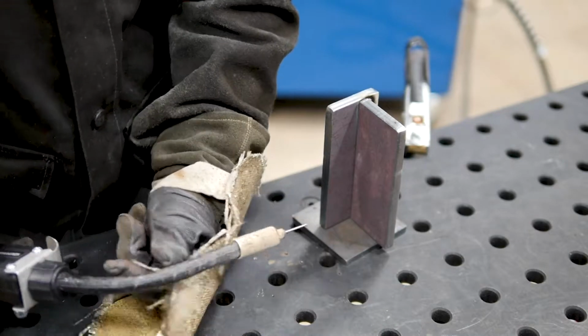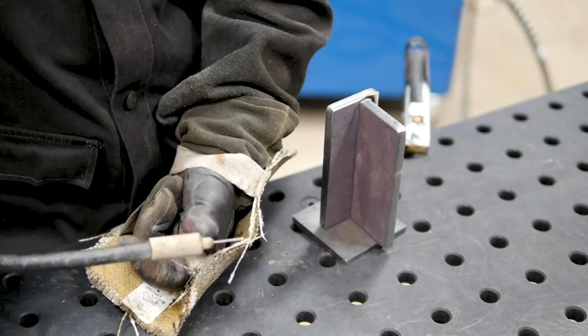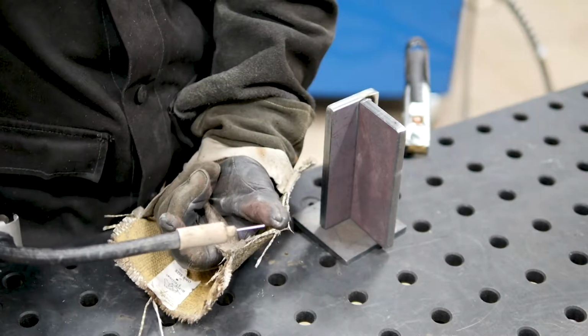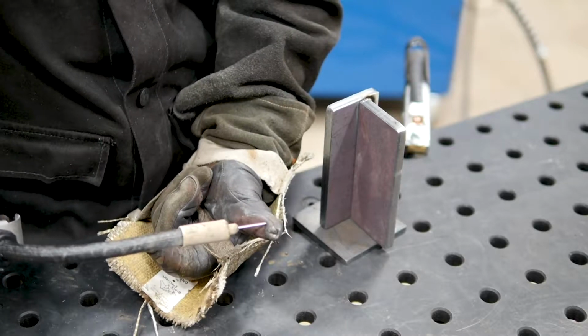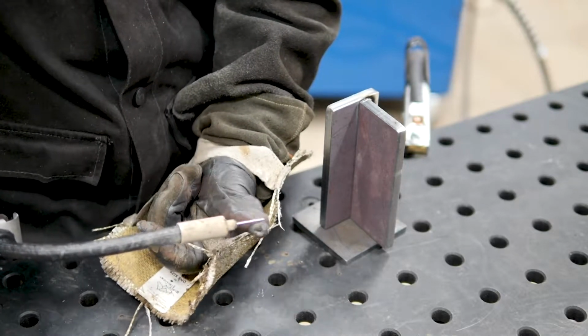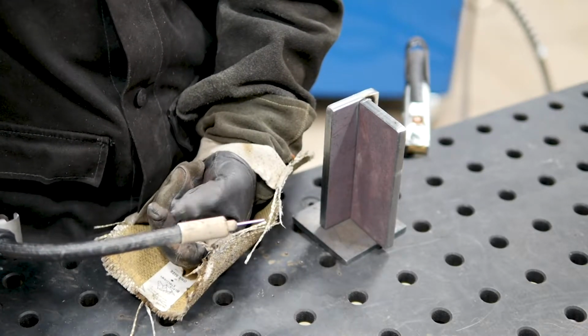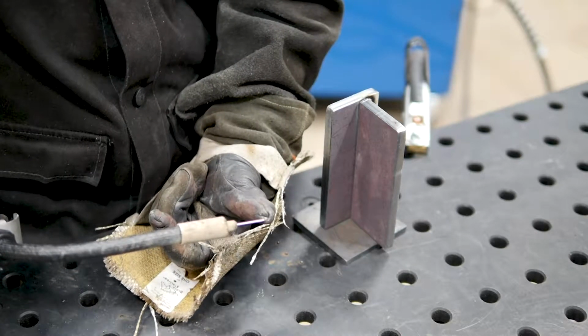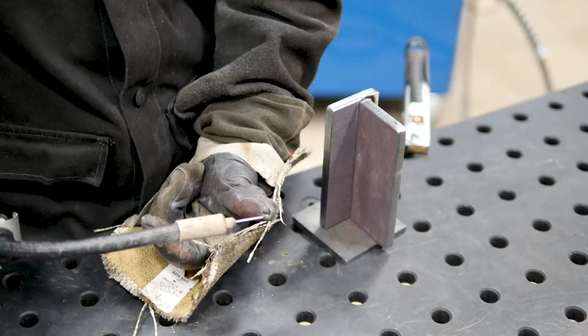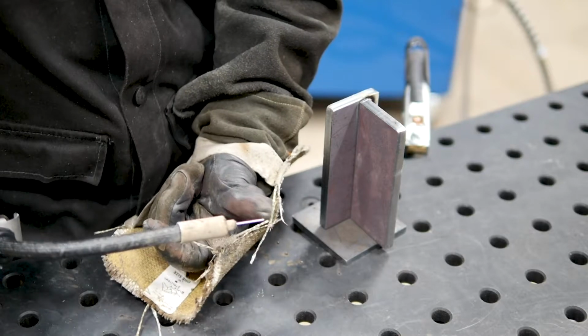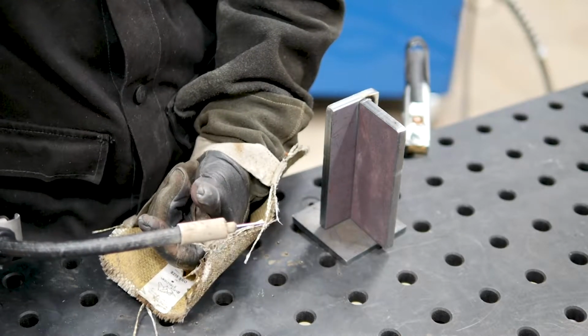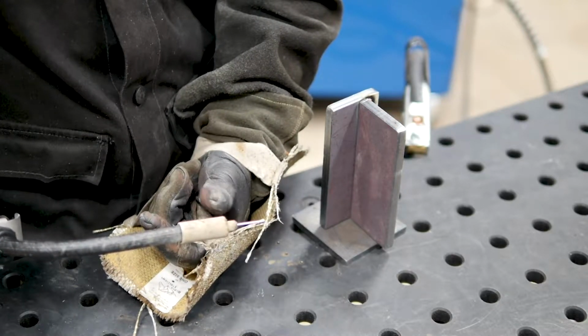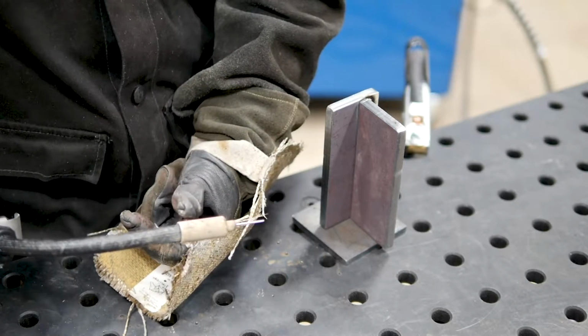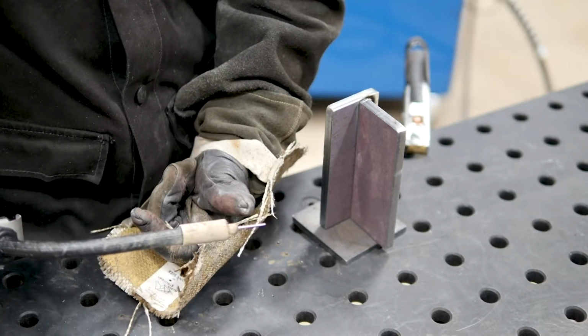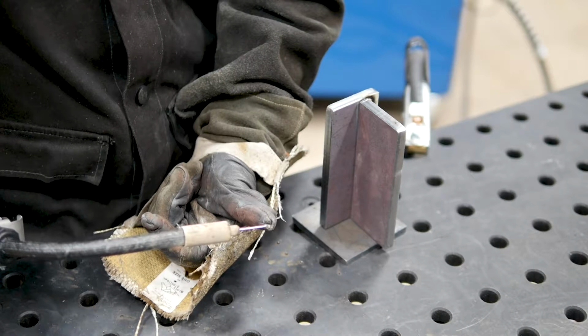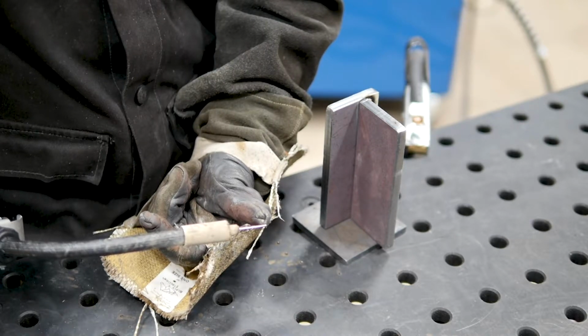What I was talking about before was contact tip to work distance. That's the face of the contact tip to the work, or the edge of the wire. So in this case, 1 inch. Now this is very, very important with this wire. When we use a constant voltage machine and we change our contact tip to work distance, the voltage doesn't change, but what does is the amperage. So if we get too long, our amperage starts to drop out. If we get too short, the amperage starts to rise and the puddle gets erratic.